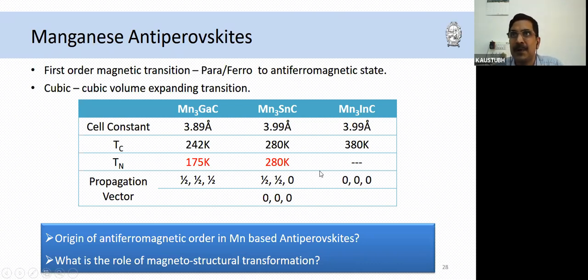So how is this happening despite the fact that the symmetry is cubic? The lattice symmetry is cubic, but the ground state is classified as antiferromagnetic. And if I change this Sn to indium, then there is no antiferromagnetic order. So the two questions that we wanted to answer were: what is the origin of antiferromagnetic order in manganese-based antiperovskites, and what is the role of the magnetostructural transformation? Because this transition, which is indicated in red here, is a first order transition. There is also a structure change, but the structure remains cubic through the phase transition. Only a volume expansion happens. So how, within the cubic symmetry, is there an antiferromagnetic ground state?